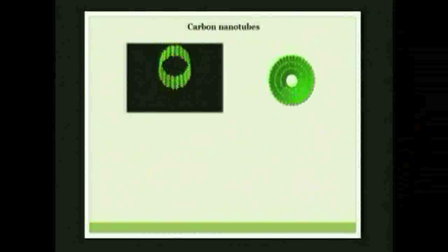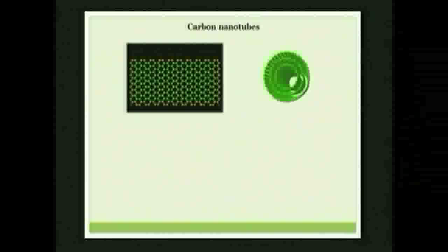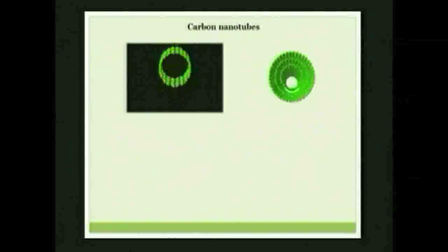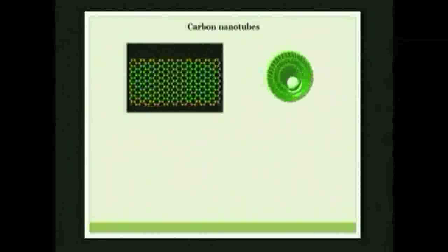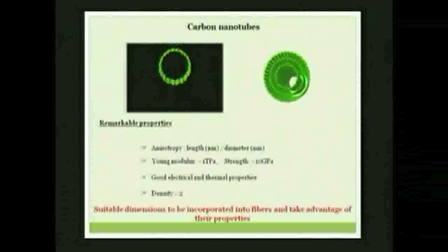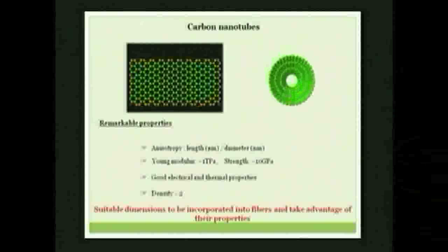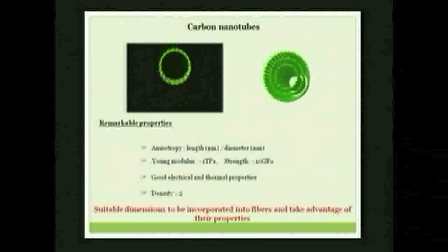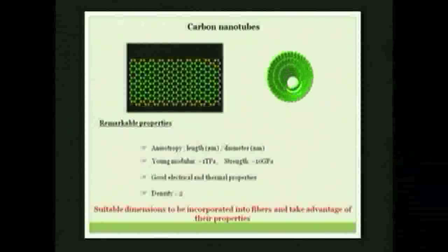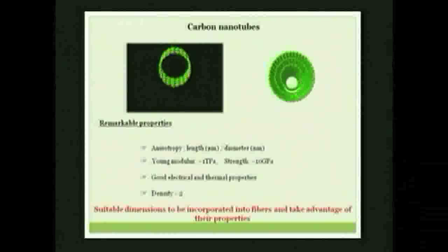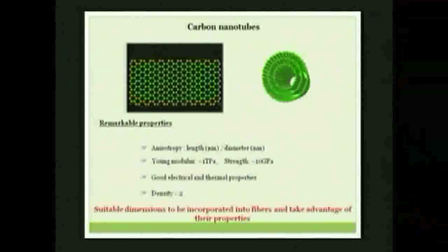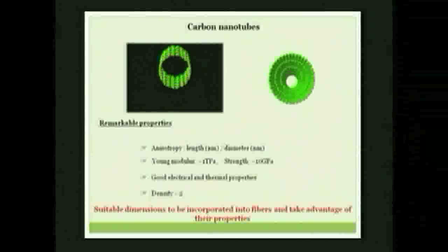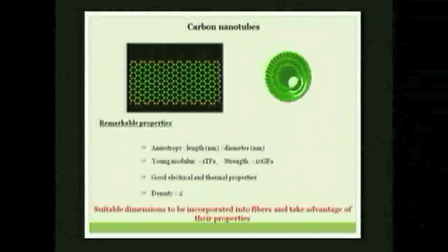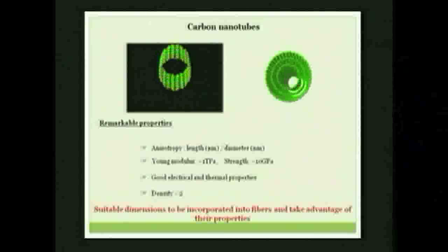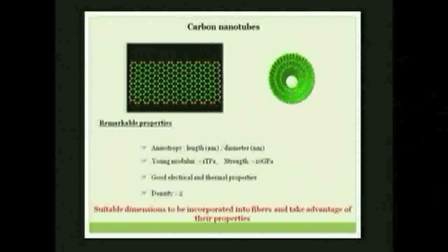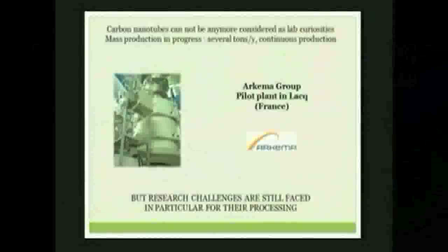So, nanocomposites with nanomaterials, of course, carbon nanotubes can be very good candidates to make nanocomposite fibers. You all know that there are two types of carbon nanotubes, single wall and multi-wall carbon nanotubes. You probably all know also that they have remarkable properties. First of all, a strong anisometry with small diameters at the nanometer scale and very high lengths. They exhibit very interesting mechanical properties, a high Young modulus, a very high strength. They have good electrical properties. The density is very, very small. And of course, they have suitable dimensions to be incorporated into fibers and to take advantage of these very nice properties.